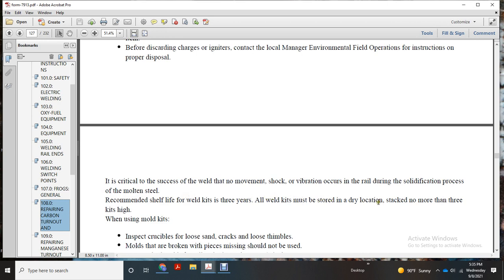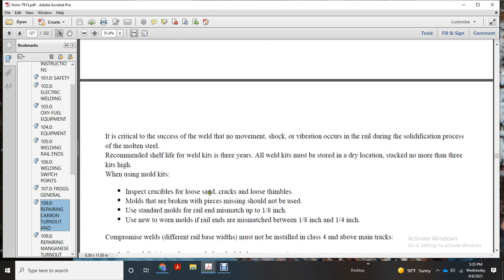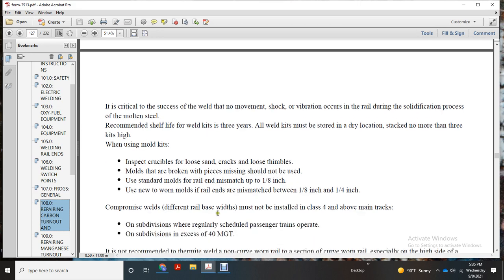Weld kit must be stored in a dry location, stacked no more than 3 kits high. When you use the mold kit, inspect the crucible for loose sand and cracked or loose thimbles. Molds that are broken with pieces missing should not be used. Use standard mold with rail end mismatch up to 1/8 inch. Use new to worn molds if rail ends are mismatched between 1/8 inch and 1/4 inch.